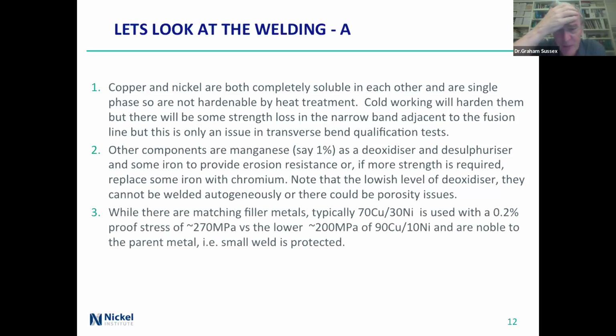While there are matching filler metals, typically 70-30 copper nickel is used with, it's got about a 0.2% proof stress of 270 MPa, which is better than the 90-10 copper nickel, about 200. And it's going to be more noble compared to the parent metal. That's what you want. You've got the small weld surface at a higher potential, and therefore it's protected potentially from any corrosion that might occur in the length of the pipe.